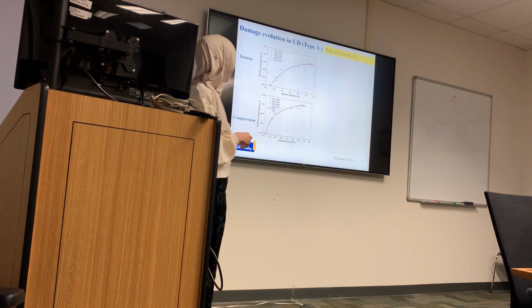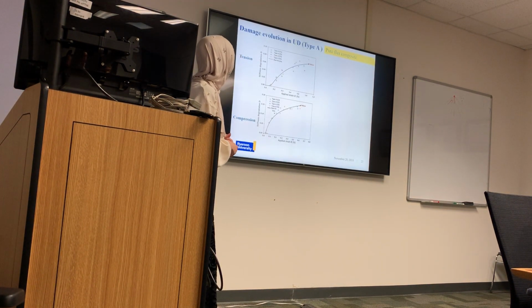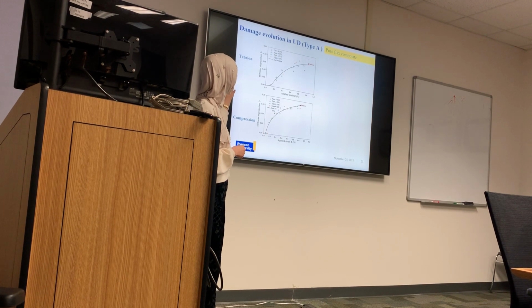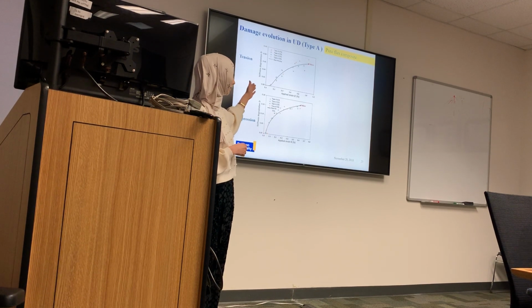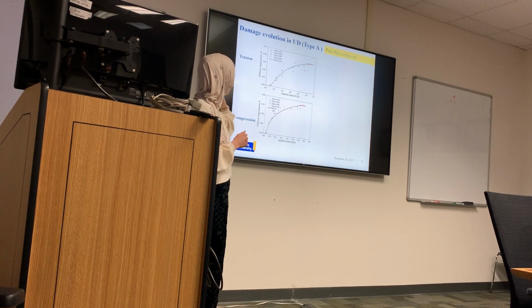We see here the damage evolution for type A. For example, for tension, we see that damage was slow up until the inflection point where it starts to increase rapidly and then they level off.